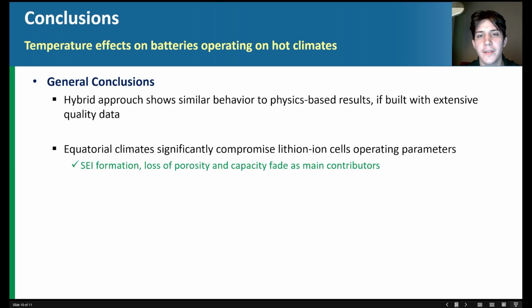To conclude our study, we've shown that equatorial temperatures significantly accelerate lithium-ion battery degradation, mainly through SEI growth and porosity loss. The hybrid PyBaMM LSTM approach proved effective for analyzing and predicting this process and enabling rapid evaluation of long-term battery health under tropical conditions. This was viable mainly due to the fact that there was sufficient data, more than 1,000 days in fact, taken hourly from the perspective of the PyBaMM's SOH function in the real ambient temperature scenario.